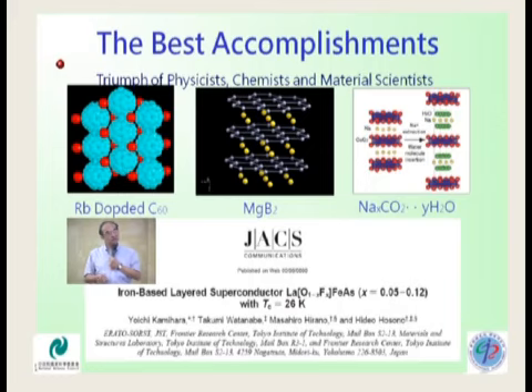Professor Hosono at Tokyo Institute of Technology reported a new compound with iron as a key element. Based on the BCS theory, or the old understanding of superconductivity, the iron component is actually no good for a superconductor because it's magnetic. When you have something magnetic, it's not compatible with superconductivity. However, this paper showed there is a superconductor with iron as the key element and TC around 26 Kelvin.